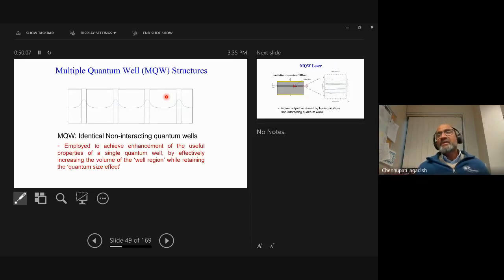Typically in a laser or infrared detector and other devices, we don't use a single quantum well, because the volume of the material you get is very small. We try to put in multiple quantum wells, but they are decoupled from each other electronically. That means the wave function of the electron in this one is here, in this one is here, and so on. Of course, you can also create coupled quantum wells, but that becomes very complex. I won't go into details of those. Multi-quantum wells allow you to create a large gain volume, which means you can get much higher output powers from these lasers, and that's why I typically end up using 3 or 5 quantum wells, depending on the particular device design.